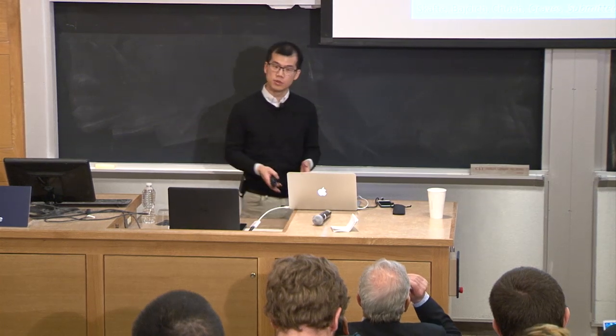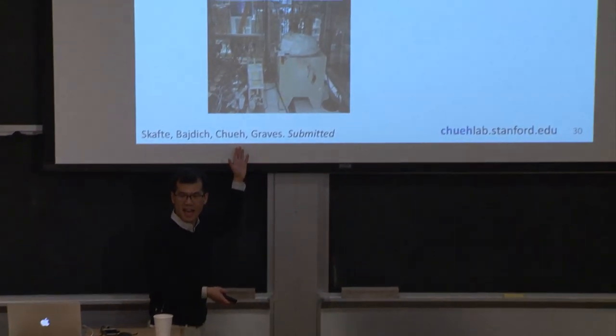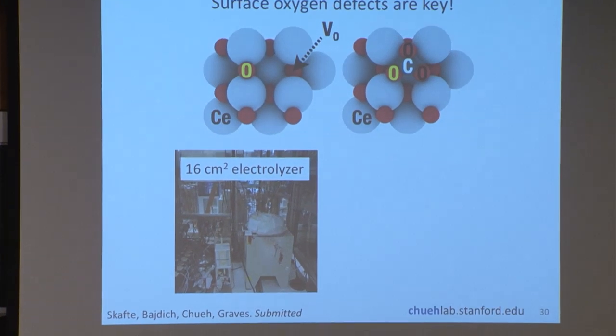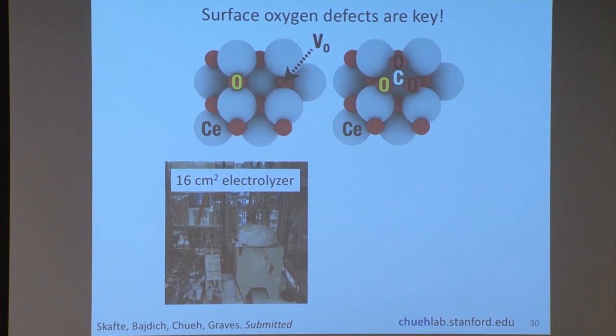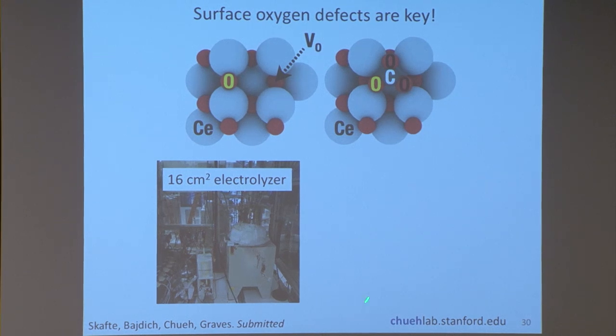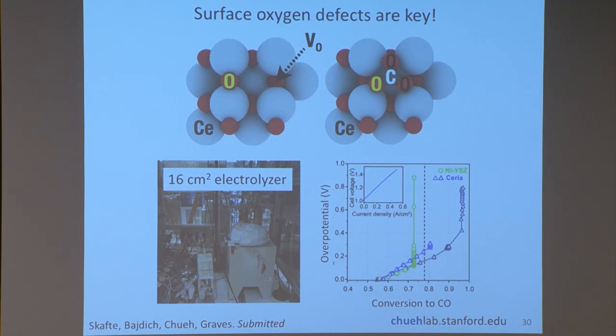Can we turn this into something useful? Absolutely. So we actually made a relevant size electrolyzer, 16 square centimeter. This is not something you do every day. This is done in collaboration with my colleagues at the Denmark Technical University, in collaboration with Haldor Topsoe, the catalysis company. And we can actually make an operating electrolysis cell containing both just nickel and nickel and cerium oxide. And this is the data. This is the overpotential, so this is how much voltage you're applying, versus the conversion to CO. So you want the conversion to CO to be as high as possible.